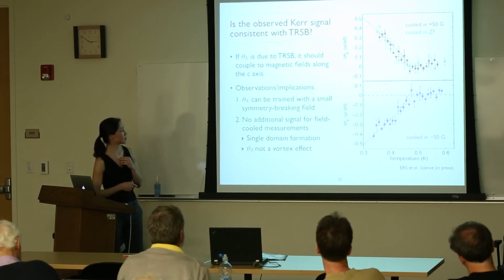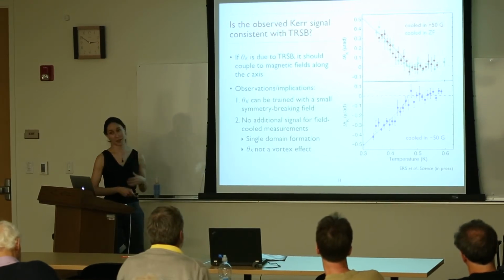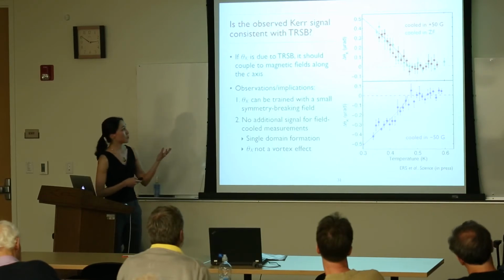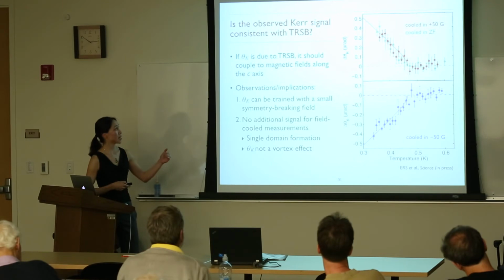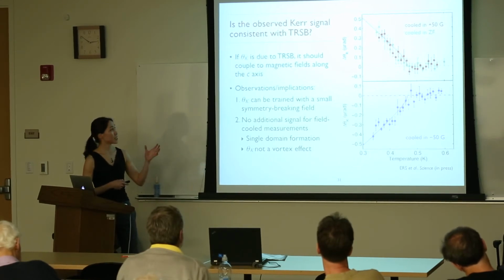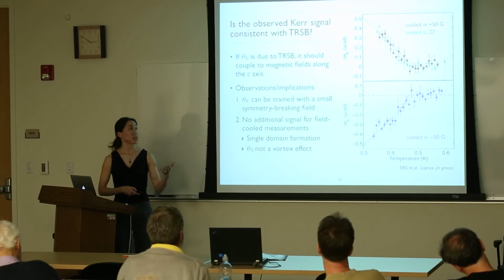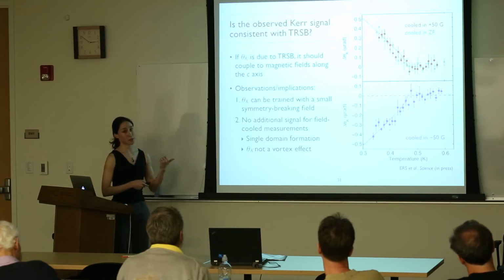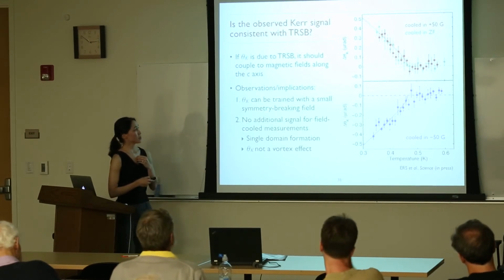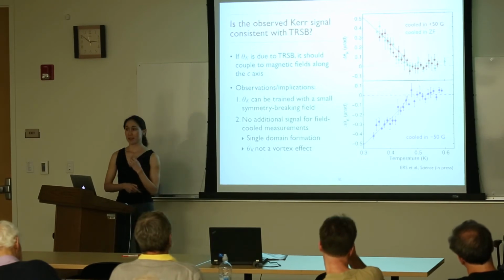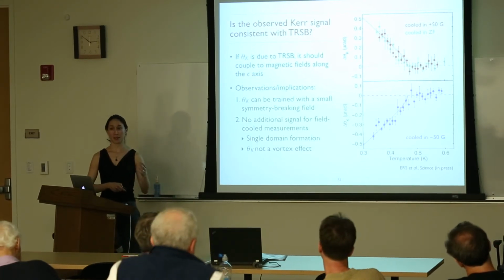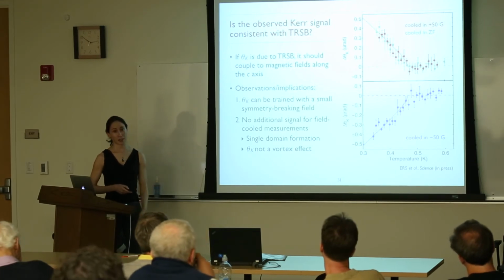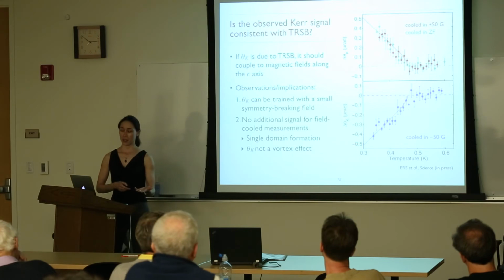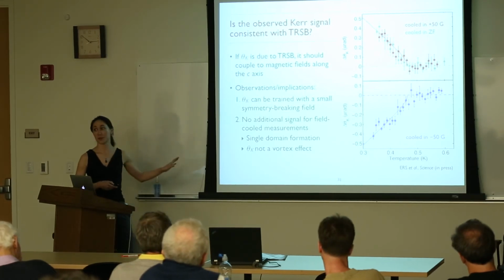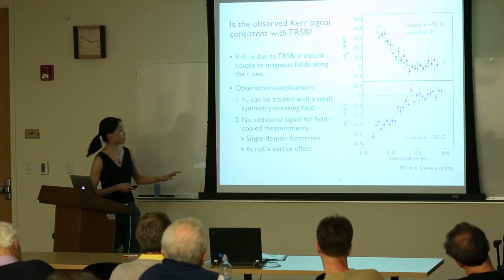And then the second thing that's interesting to note is that the zero field-cooled signal is the same size as the field-cooled signal. What I mean by that is, if you think back to an earlier slide where I was talking about domain formation, you would normally expect that in zero field, whatever Kerr effect you see would be random in sign and random in magnitude. That actually wasn't what we observed. Basically, all of the zero field measurements were the same size. Most of them were the same sign, which is interesting. What it suggests is that the domains, if they're being formed, are very large. That actually turns out to be consistent with what other people have measured using crystals from the same group. So it's not entirely outlandish.